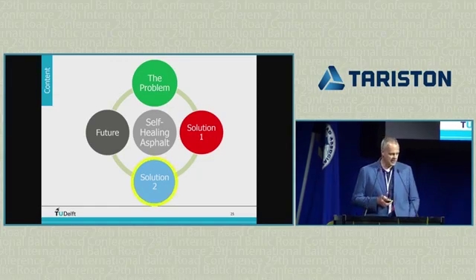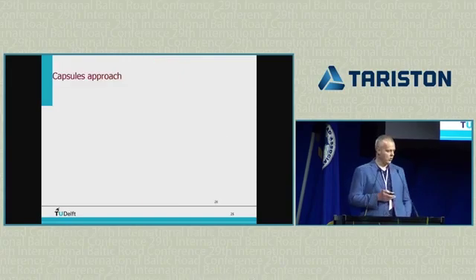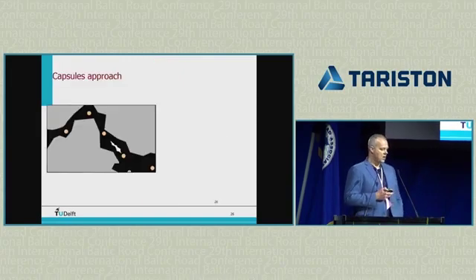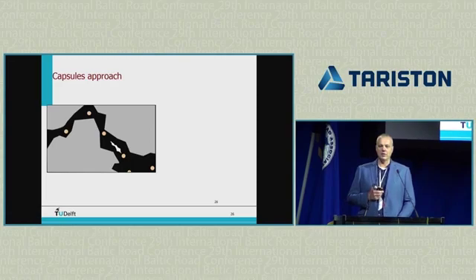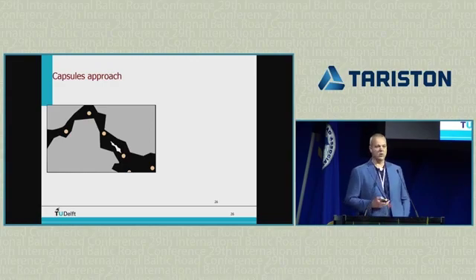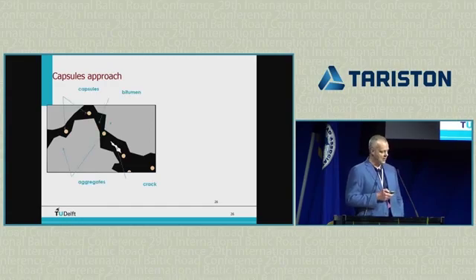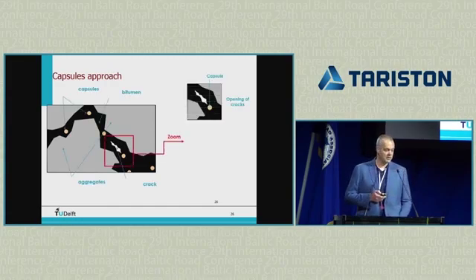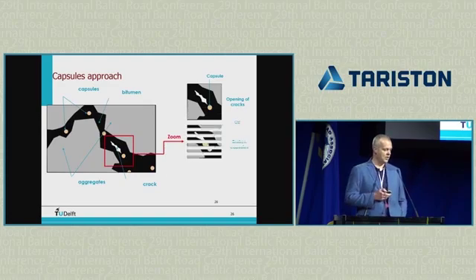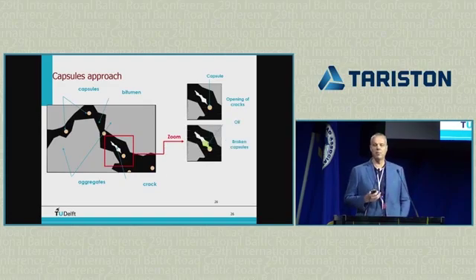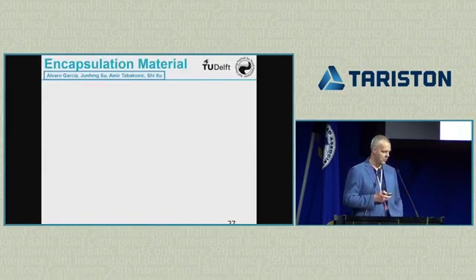But to overcome this aging, we're working on a different approach, which is a capsule approach, where we actually put small capsules in the material with rejuvenator inside. So you can put rejuvenator later on the aged bitumen, but you can also put the capsules already inside your material. So the capsules contain the rejuvenator. If you get a crack again, this opens the capsule, rejuvenator comes out, and then softens the binder and makes it more flexible again. So this is also something we are working on.